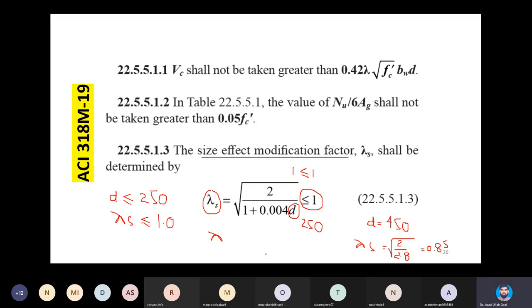For example, if you will put D 200 in this equation, so 200 into 0.004, then plus 1 will give you 1.8. So 2 divided by 1.8, and then taking under root of it, will give you answer more than 1. But you have to limit it to 1. So for beams which are 250 or below, you have to select lambda s 1. And for beams deeper than 250 millimeter, this lambda s will give you a value which will be less than 1. So in this way, you will be limiting your VC based on this size effect modification factor.